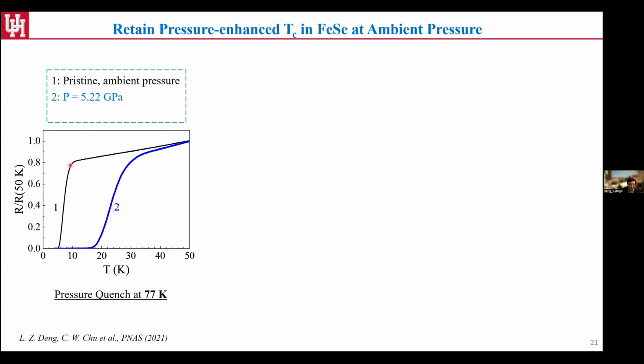That makes a good difference between the pressurized state and the ambient state from the TC point of view. And then we immerse the cell in the liquid nitrogen environment. That's why we have the 77 Kelvin here, and we quickly remove all the pressure completely, and then that's what we got. So when we warm up again, we got the red curve. So very beautifully, the TC didn't go back to 9 to 10. It retains above 20 Kelvin, even though it's not ideally matching the blue curve, but that's kind of doubling the TC. That's already some exciting results.